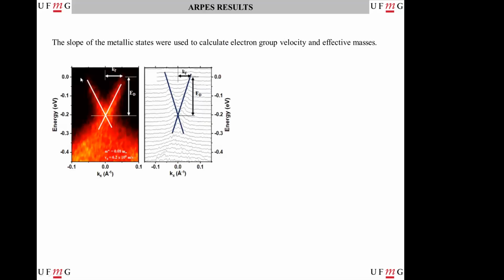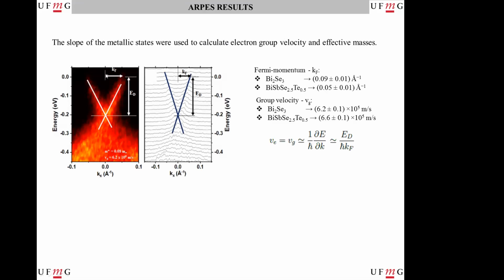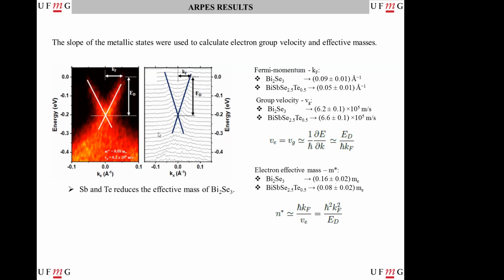Another thing that we did is that we used the slope of the metallic states in the band gap to calculate quantities like the electron group velocity and the effective mass of the samples. Here we took the cone, and using the quantities that we measure here and some formulas, we can retrieve the Fermi momentum of each sample and the group velocity of 6.2 and 6.6 for bismuth selenide and the quaternary sample. And from that, we measure that the electron effective mass of the quaternary sample is 2 times smaller than the Bi2Se3 sample. So the conclusion that we got from the ARPES result is that the antimony and tellurium reduce the effective mass of bismuth selenide.